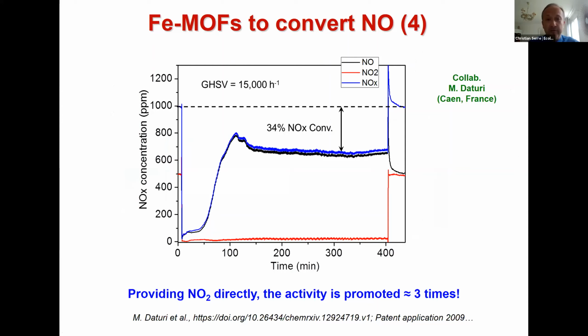It contains a lot of NO2 because it's easy to oxidize NO into NO2. And so here we added a mixture of NO2, 50-50 in percentage, and then we increased by 3 the velocity. And surprisingly, the conversion was multiplied by almost 3, which means that NO2 is promoting a lot the catalytic conversion of the NOx into nitrogen.